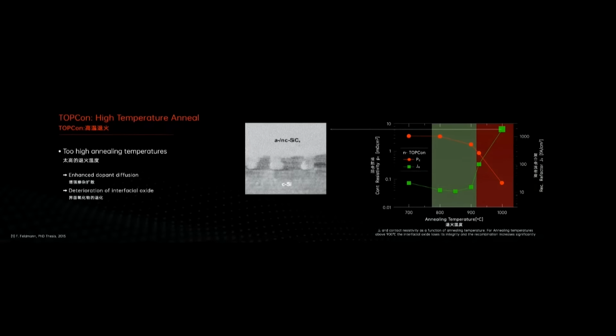However, if we go to too high temperatures, then two adverse effects happen. On the one hand side, we drive in too many dopants in the material, which increases the recombination. And if we go to excessively high temperatures, we even see a huge deterioration of the tunnel oxide layer. And then you can see what happens here. This is a worst case scenario, that the tunnel oxide layer balls up and the silicon layer on top of the crystalline silicon can epitaxially regrow, and we virtually do not have any surface passivation left.